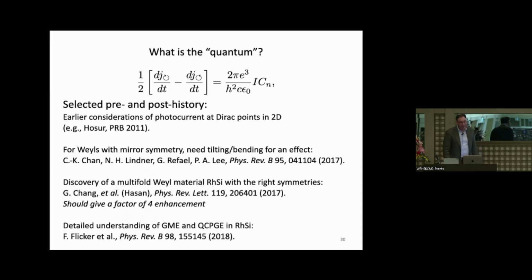And here's the idea of the experiment, which is all optical, so no contacts. Basically, you shine a pulse of light into the rhodium silicide. That creates a brief burst of photocurrent. That brief burst of photocurrent, you can measure the radiation it produces and see, essentially, overall magnitudes are tricky to measure from the radiated field, but you can at least see, does this depend on frequency the way the theory would suggest?